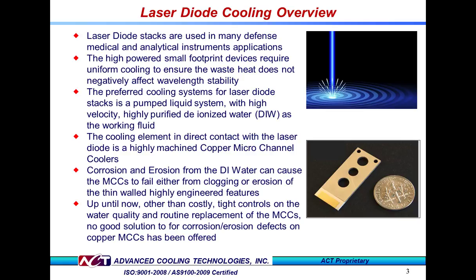A common cooling solution for these laser stacks is to use a pumped liquid system, where the working fluid removes the waste heat and dissipates it through a chiller or other heat exchanger. Deionized water is frequently selected as the working fluid. To ensure long-term reliability of the cooling channels, the water quality needs to be closely maintained for several parameters, including temperature, flow rate, dissolved oxygen, pH, and resistivity.